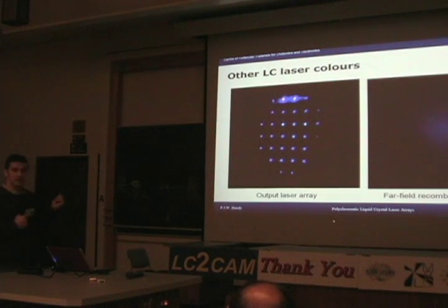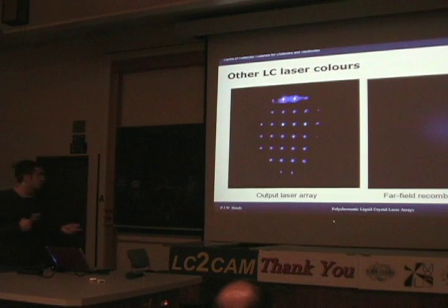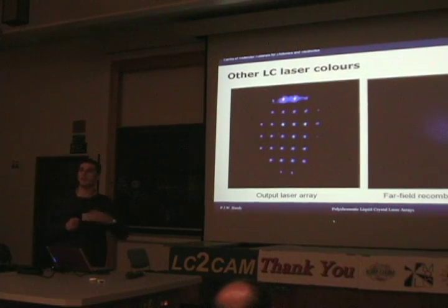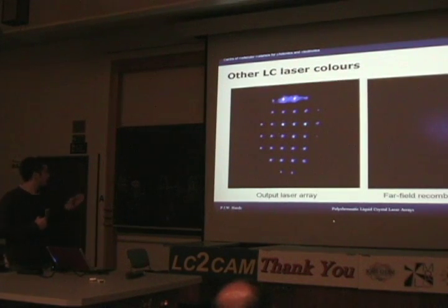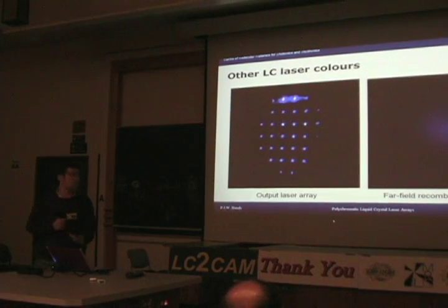This is a much weaker laser than the green and the red laser, partly because your eye is less sensitive to blue, so it appears darker relatively, but also simply because of the close proximity between the dye's emission and absorption spectra. So some of the emitted light is actually reabsorbed by the dye again.